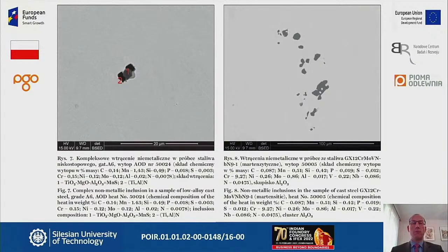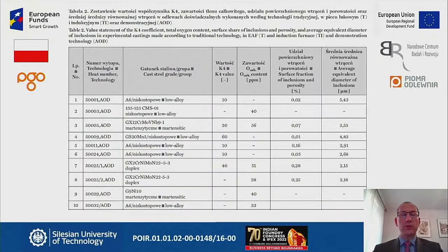And obviously, to be sure that we will obtain the mechanicals at the level we demanded, or we wrote in the project, we checked a lot of samples in the matter of non-metallic inclusions, the precipitations of many phases, etc., to be sure that their level is as low as standards say, and that their shape, size, and distribution is the best. And what else? We checked the K parameter and total oxygen content because they were milestone parameters, yes? So we checked them for all of the steel we produced.